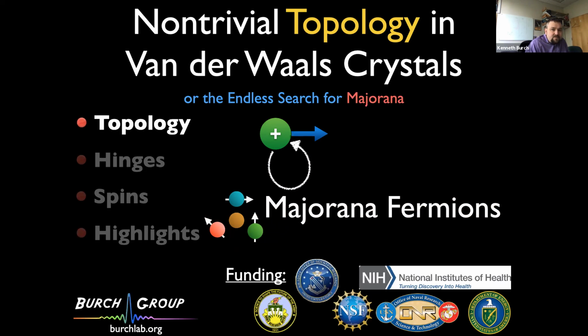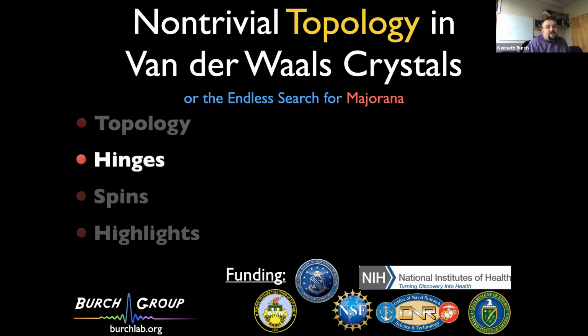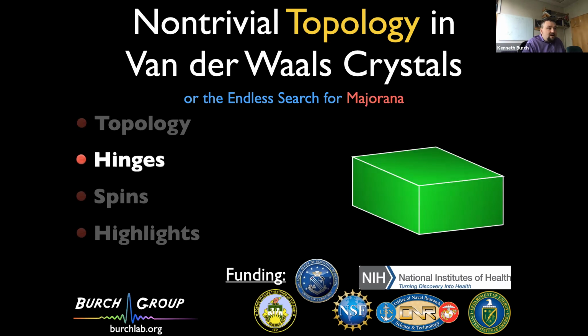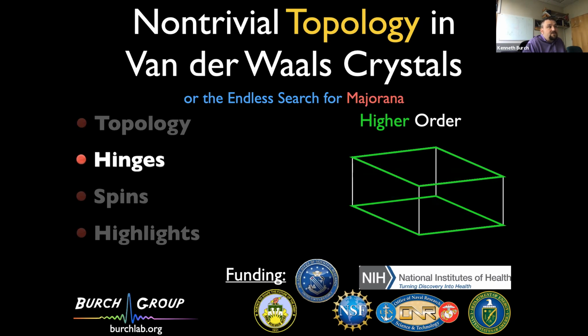So the first system that I'll tell you about is a new way of looking at this topological business that emerged in the last 3 years. One of the key signatures of a topological phase is the so-called bulk-boundary correspondence, where the non-trivial bulk leads to new modes at the boundary. Typically we think of this as, say, surface states on the surface of a TI, but it turns out under the right conditions, these states that emerge can then be gapped out, and you can get even lower dimensional modes. In other words, rather than getting, say, a 2-dimensional mode on the surface of a 3-dimensional system, you can actually get a 1-dimensional mode. And this is evidence of the fact that you have the so-called higher order topological phase.